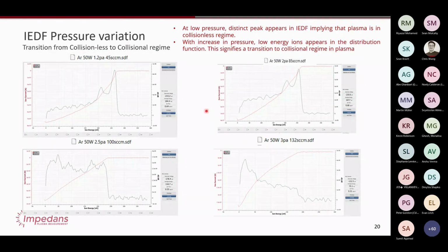Let me give you some more examples of pressure variation, because I want to show that over a very small pressure range, you can have really dramatic differences. So this diagram over here is real data from our chamber Impedans. This was 50 watts on the bias, 1.2 pascals, and 45 sccm. This was argon, and that's a relatively low pressure.